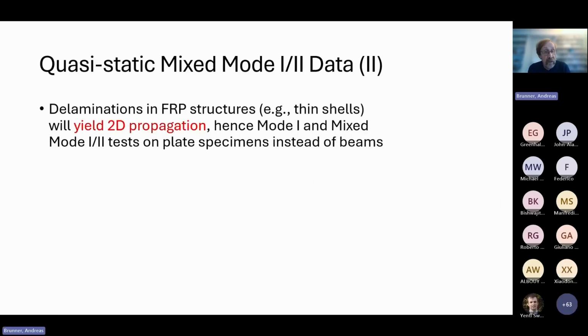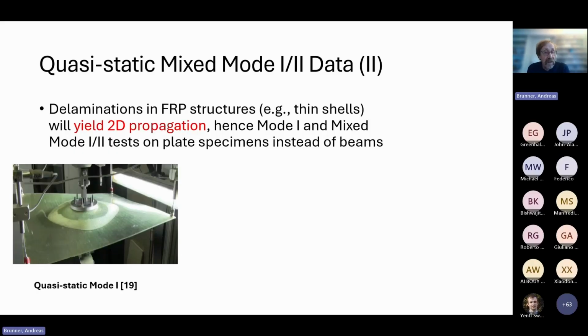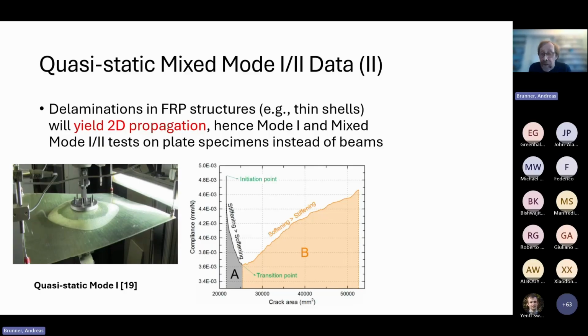Now, it has already been mentioned by John Allen that, of course, in real structures, for example thin shells, which represent a lot of the structures that we have, will yield two-dimensional propagation, which is different from what we get in the beam specimens. This is taken from the PhD thesis of Ida Camiselle Molares at EPFL. This is a quasi-static mode 1 test on a plate, which had a circular starter crack at the center, and then was loaded in mode 1. There were quite some phenomena that you wouldn't expect, or would not be able to see in the beam-like specimen. So there's a stiffening, softening behavior, and there's a transition point somewhere.